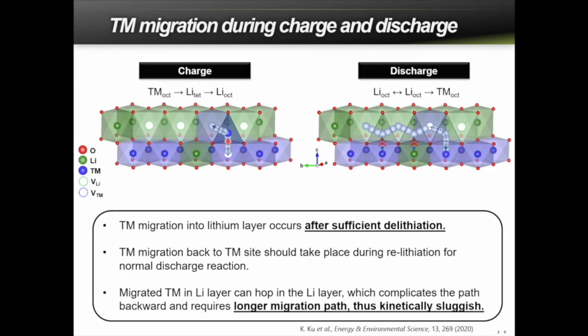But unfortunately, some of the transition metal in the lithium layer that has migrated can also migrate in the vacant lithium layer, hopping farther from the original site. And if it happens, it very much complicates the path backward during the relithiation and requires a longer migration path. So the lithiation and delithiation processes can be asymmetrically different. Compared with the simple hopping up of the transition metal during the charge, the complicated and longer path of transition metal during discharge is believed to result in the particularly sluggish discharge reaction, because those incoming lithium have to interact and then push these transition metals back to this.